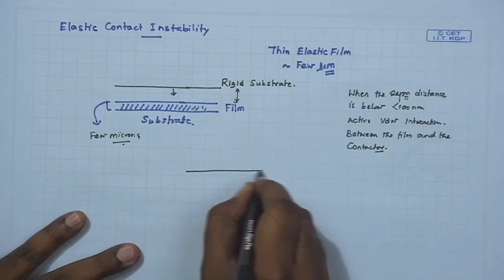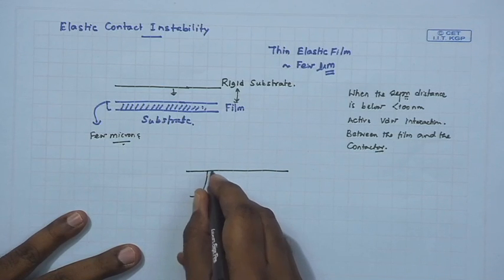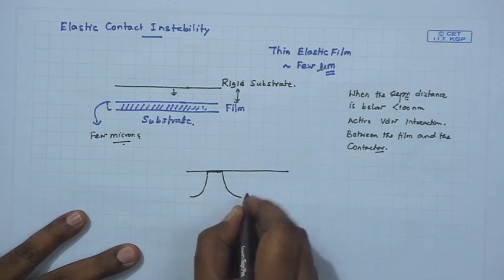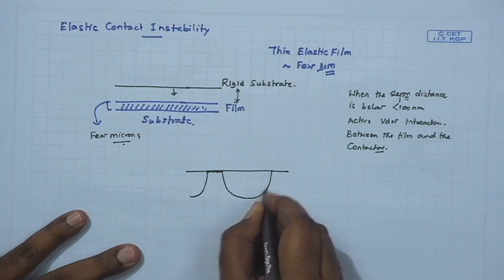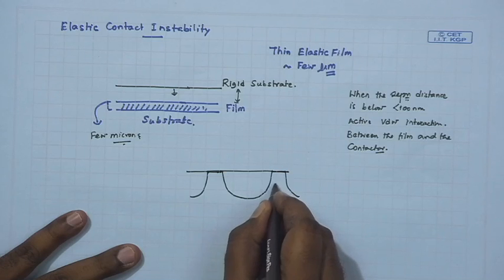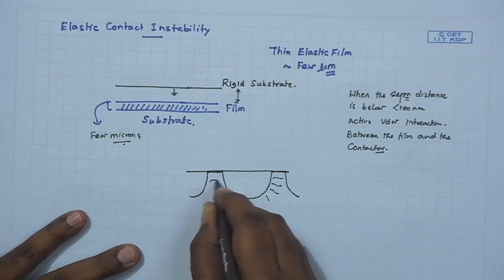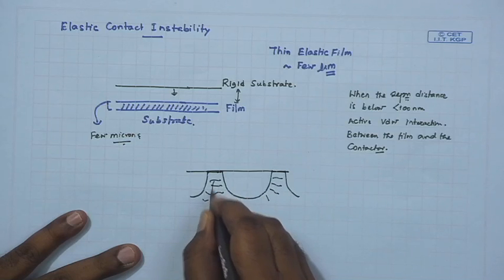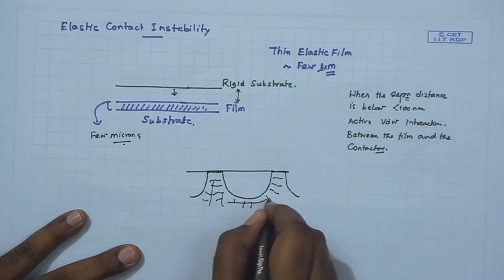But look into the material property of the film. It's not a liquid, right? Heated beyond its glass transition temperature. It's a cross-linked elastomer. So what happens is, as part of the film, I'll just draw an exaggerated view, as part of the film jumps and comes in contact with the contactor, it leads to significant stretching of the cross-linked matrix. And therefore, the cross-linked matrix, on the other hand, tries to pull it back. So there is now a competition again.